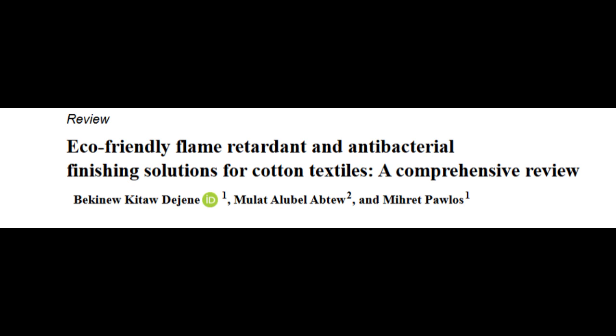That trade-off again, balance between safety and feel. Always a consideration. You mentioned a nanosilica intumescent system that sounded good, though. Yes, they combined nanosilica, SiO2, polyethylenimine, PEI, and phytic acid, PA, using LBL. It achieved a high LOI, low char length, good char residue, and significantly cut down the heat release rate and total heat released. And importantly, it didn't seem to weaken the fabric much.